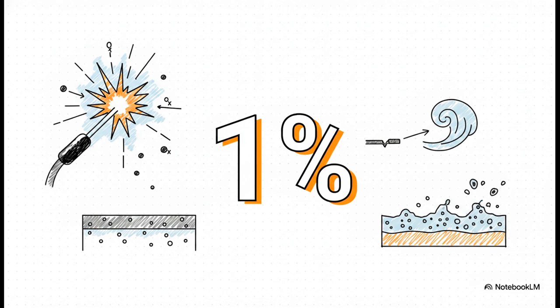Nitrogen and oxygen absorption usually kicks off from poor gas shielding around the arc. If you get as little as 1% air entrainment in the shielding gas from, say, a tiny draft or a tiny leak in the line, it's going to cause distributed porosity. And if that air contamination creeps up just over 1.5%, you are guaranteed to get gross, completely unacceptable surface-breaking pores.